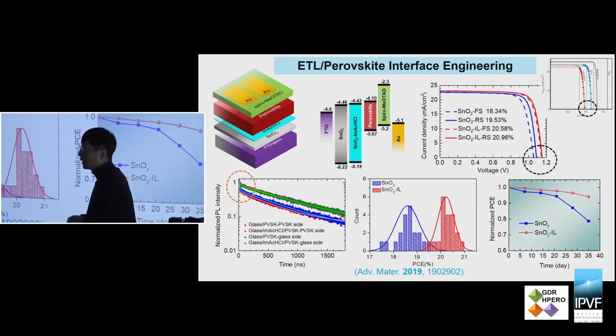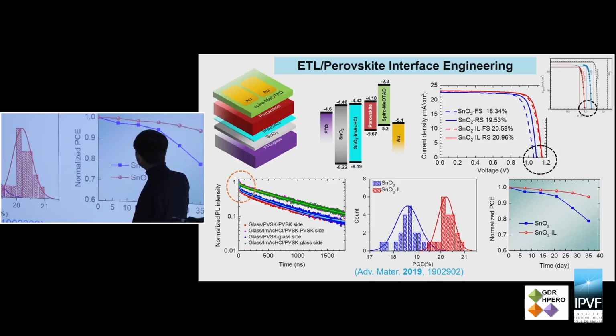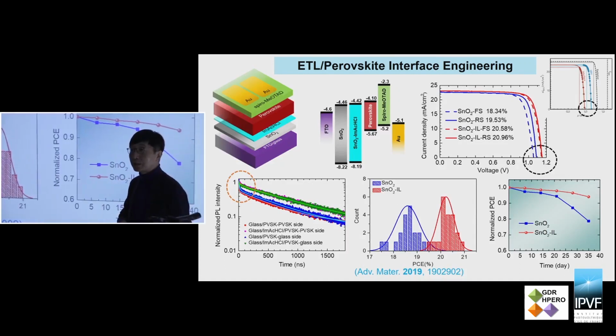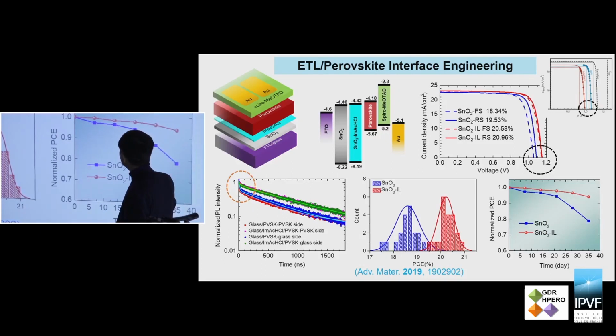In that case, if you introduce some kind of functional materials in between the perovskite and the tin oxide, because the tin oxide perovskite interface is a heterojunction, so you probably created imperfect interfaces. And then if you introduce some kind of bifunctional material with chemical bonding with both the perovskite and the tin oxide, then we found that the open circuit voltage increases, there is no significant change in short circuit photocurrent density, and we slightly increase the fill factor.